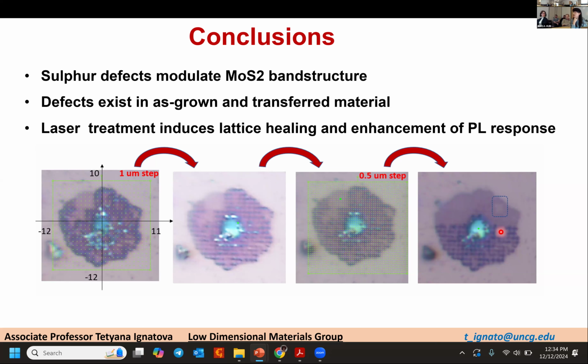Yeah. What is interesting, and why we are thinking about healing, is that this enhanced optical response is not temporal. If a sample was treated perfectly to the maximum of enhancement, it will hold this optical response over days, until normal aging factors will significantly suppress the optical response. Yeah. And I did get it right that it happens pretty much equally for the silicon oxide substrate, which has photo traps, and for sapphire, which does not have any photo traps. Yeah. Yes.